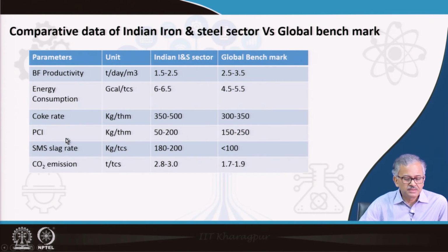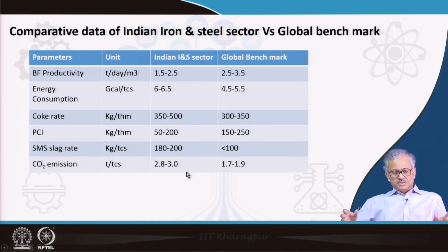SMS slag, that is the steel melting slag, is 180 to 200 kg per ton of crude steel, and the global benchmark is less than 100 kg. CO2 emission, tons per ton of crude steel, in India is 2.8 to 3, which is very high compared to the global benchmark of 1.7 to 1.9, and India is desperately trying to reduce this emission to maintain the environmental protocol. They have to reduce it to 2.2 tons per ton of crude steel production.